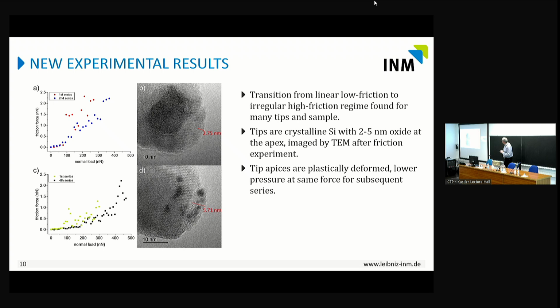So in the upper panels, we took out the tip after doing two experiments and went to TEM and looked at the tip. I don't know how well this can be seen here, but this is a silicon tip, and you can see the silicon atomic rows up to two and three-quarter nanometers before the end of the tip, and then you have the amorphous oxide. So the experiment is actually done with amorphous silicon oxide. In the lower panel, you just see a tip. The green dots are the very first experiment, so again, 80 nanonewton for the transition. And then the black is actually the fourth. And it's a similar thing here.